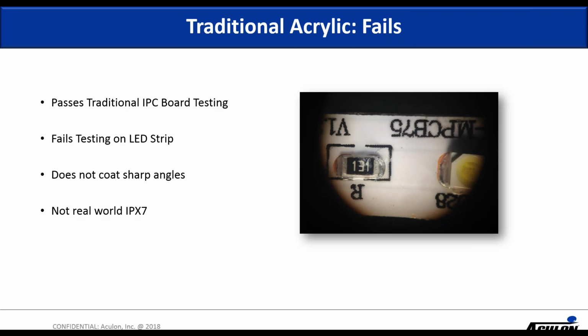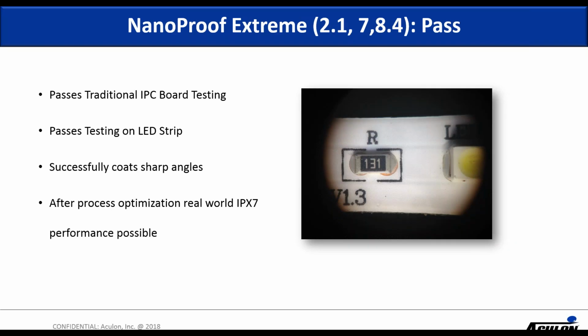We saw the same exact thing with a traditional acrylic and several other coatings. Again, they did not protect the edges, slumped, and did not give real-world IPX7 performance, even though they did just fine on the IPC boards. Now getting into the NanoProof Extreme level products, 2.1, 7, and 8.4. All of these pass the traditional IPC board testing, but they also pass the LED strip, and that's because they have a special feature which allows them to actually maintain their thickness around the edges and provide a uniformly thick layer around all the 3D components. The sharp angles are protected, and you get real-world IPX7 performance.